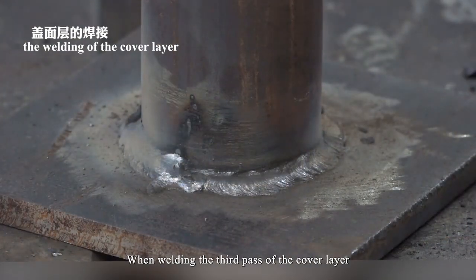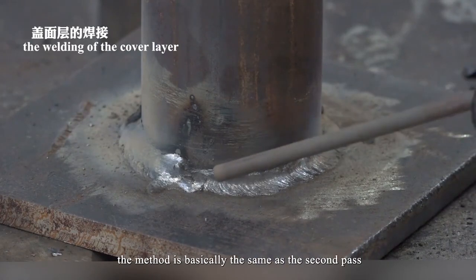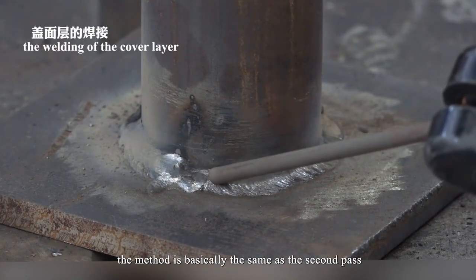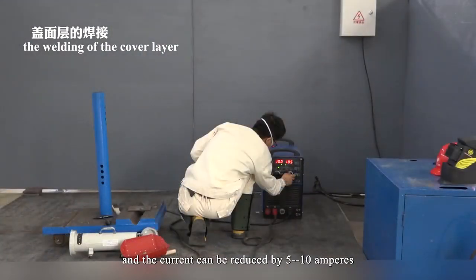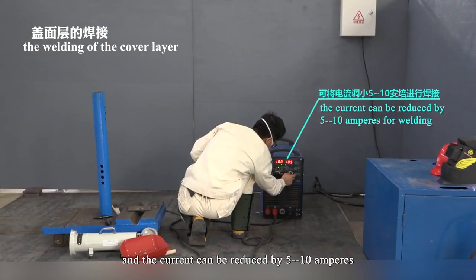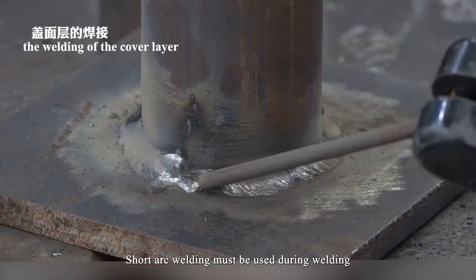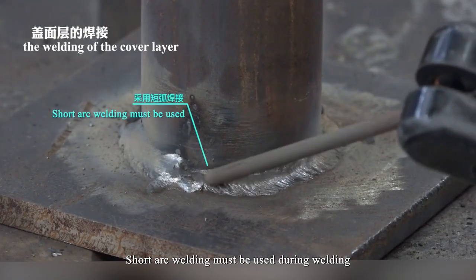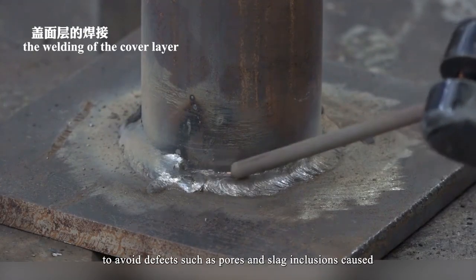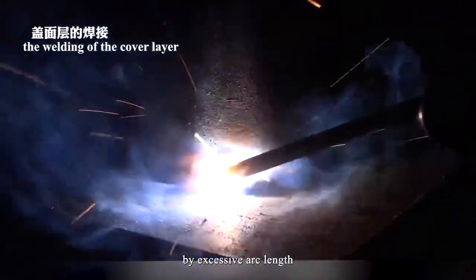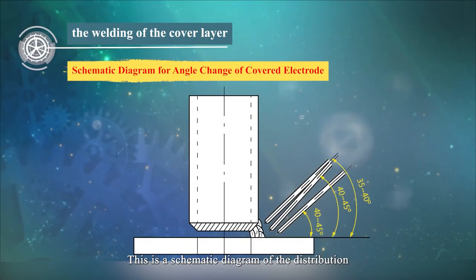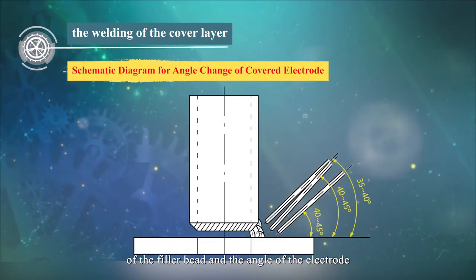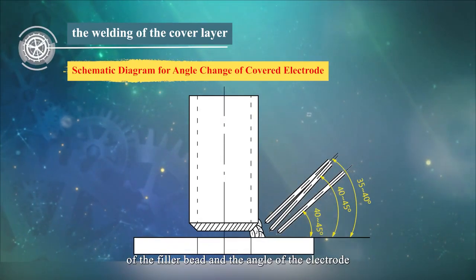When welding the third pass of the cover layer, the method is basically the same as the second pass, and the current can be reduced by 5 to 10 amperes for welding to prevent undercut. Short arc welding must be used during welding to avoid defects such as pores and slag inclusion caused by excessive arc length. This is a schematic diagram of the distribution of the filler bead and the angle of the electrode.